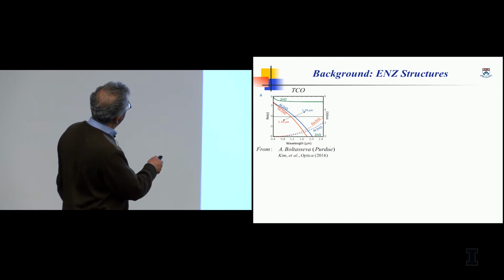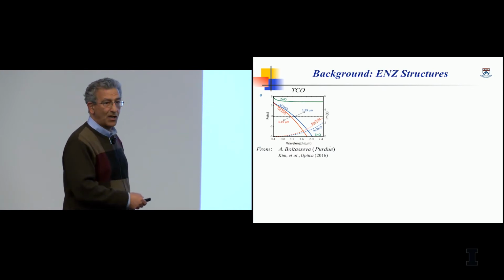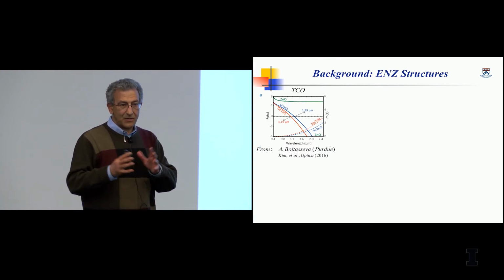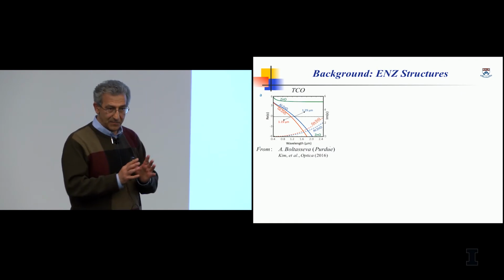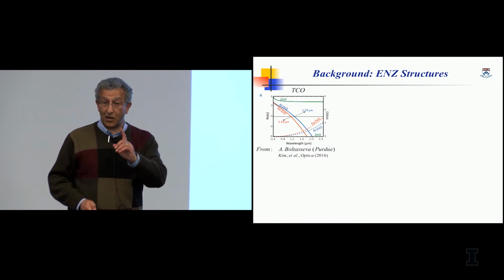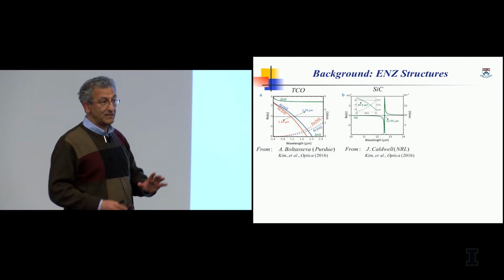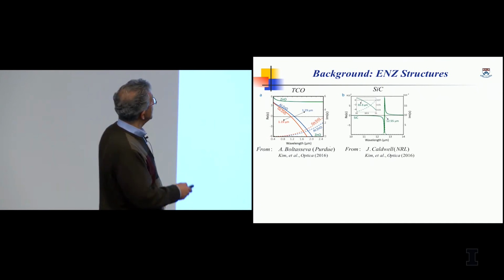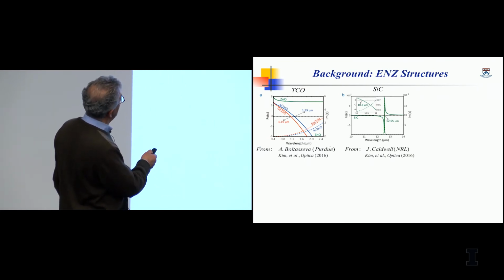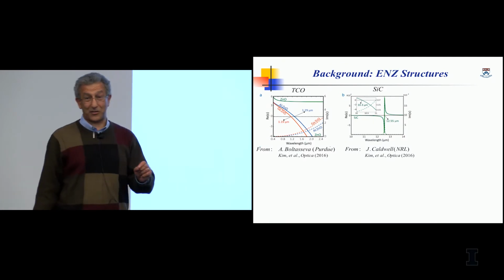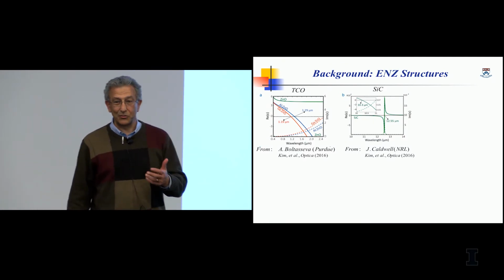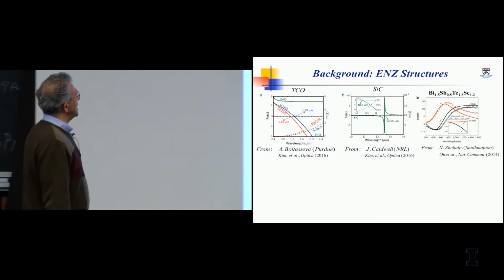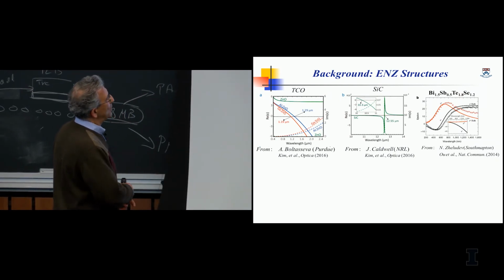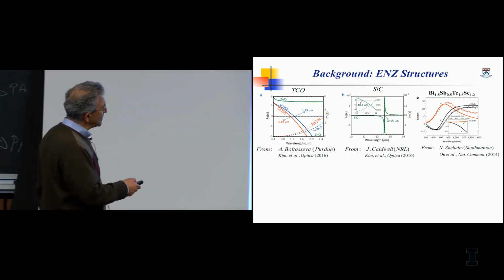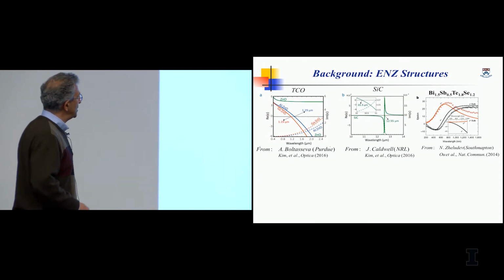Now, these materials, by the way, the imaginary part of permittivity is not too small. So the range of the application of this material is limited. However, if you go to mid-IR, silicon carbide, excellent, by the way, in this aspect. Silicon carbide has a zero crossing of permittivity at 10.3 micron. And that's very close to CO2 rates that we have there. And so we have it also in topological insulator that N. Zheludev found.